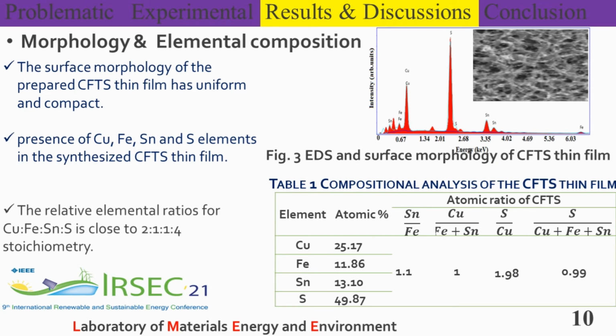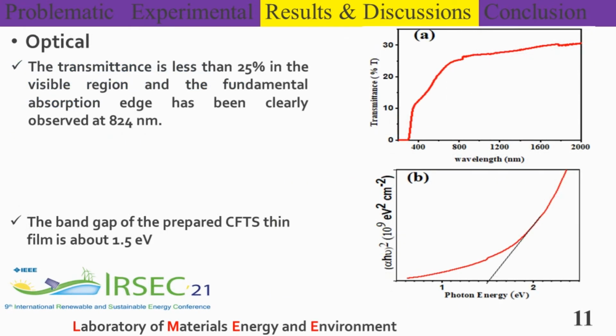For morphology and elemental composition analysis, the surface morphology of the prepared CFTS thin film is uniform and compact. The energy dispersive spectroscopy confirmed the presence of copper, iron, tin, sulfur elements, with stoichiometry. Also, the optical characterization has been performed. It is shown from this figure the transmittance is less than 25% in the visible region, and the fundamental absorption edge has been clearly observed at 824 nanometers. In addition, the band gap of the prepared CFTS thin films is about 1.5 electron volts.